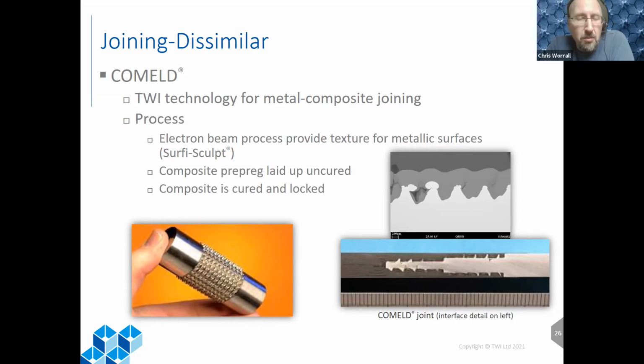So over the years, going back to the early 2000s, even before that for the PCM technology, we've been looking at ways of improving the performance of a joint between a composite and a metal. And what you can see behind me is an example of Surfi-Sculpt, the metal surface treatment used in Comeld. So that little metal cylinder that the hand is holding, that's a Surfi-Sculpted metal. Think of it like additive manufacturing, but rather than additive, it's displacive manufacturing. So we're locally moving bits of metal around on the surface to produce 3D features, which then grip into a composite to provide an integral mechanical locking or integral mechanical attachment that then enhances the adhesive bond between the metal and the composite, giving us a stronger joint.